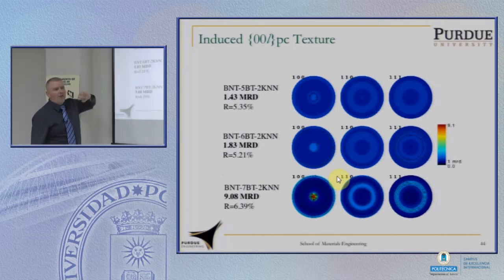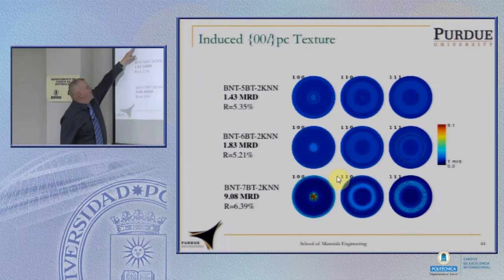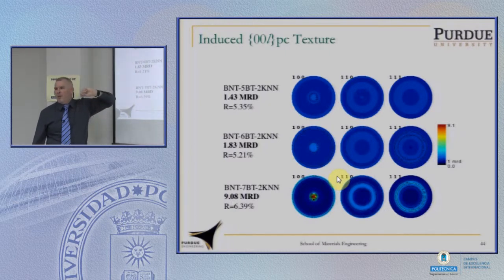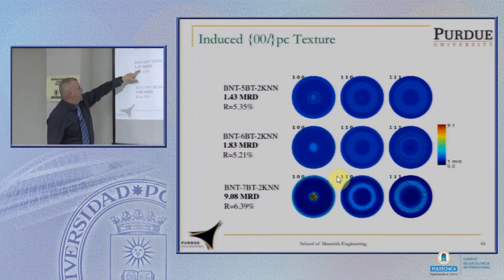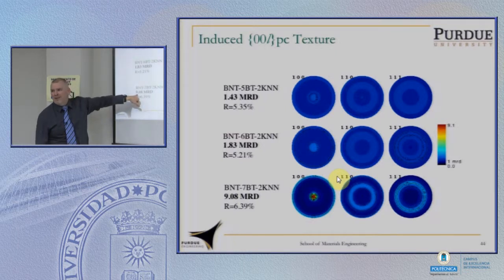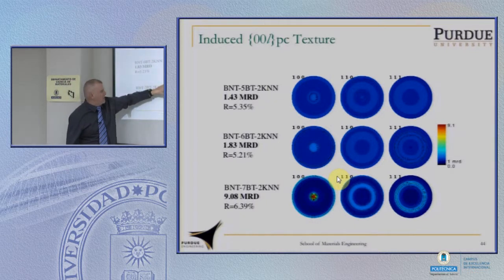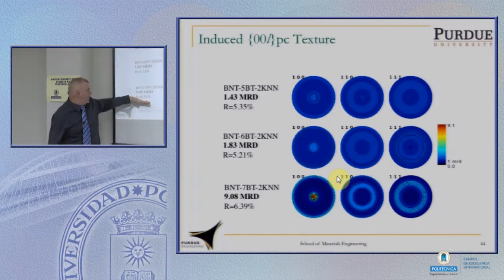We use the same term of MRD. MRD 1 means random, 1.4 means it's 40% more oriented than a random sample for the particular orientation you're looking at. In this case, it would be 83%. In this case, it would be 900%. Okay, so what that says, for these materials, if we look at the C-axis, the 100, if we look at that orientation, there is 9 times the likelihood of finding that orientation as you would find in a random material. So these are pretty strongly oriented materials.